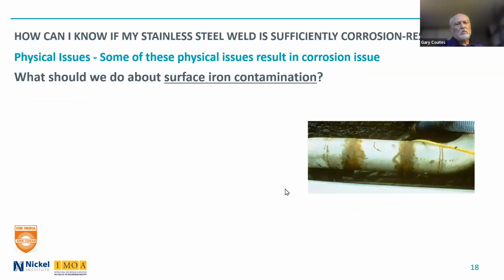So what should we do about surface iron contamination? Let's take that at first. Well, first of all, you have to find it. As I mentioned, when it's just iron on the surface, you can't really distinguish it from the stainless steel, so it has to rust. So you really have to find it first. I like the idea, if you can, and it doesn't work in all cases, of hosing down the piece of equipment, assuming it's all stainless steel, throwing a plastic sheet over it and letting it sit. If you know it's going to rain, you can just put it outside and let it sit in the heat and humidity and in the rain, but you really have to get that surface iron to show itself through rusting to actually see what it is.